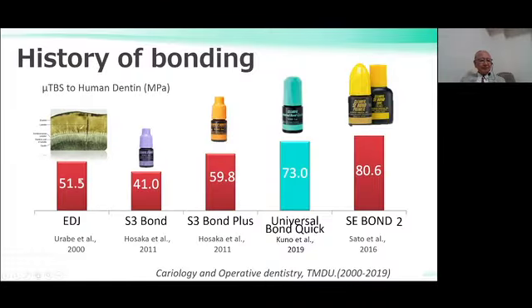Also, this is the weak point of the tooth, natural tooth itself. Many years ago, we evaluated the tensile strength at the enamel dentin junction with a very similar shape of specimen like the bond test method. The result was 50 megapascal. Nowadays, the bond strength of the composite resin to dentin was much stronger than the tensile strength of the enamel dentin junction. So we can create a very durable restoration, a composite of tooth and composite resin.